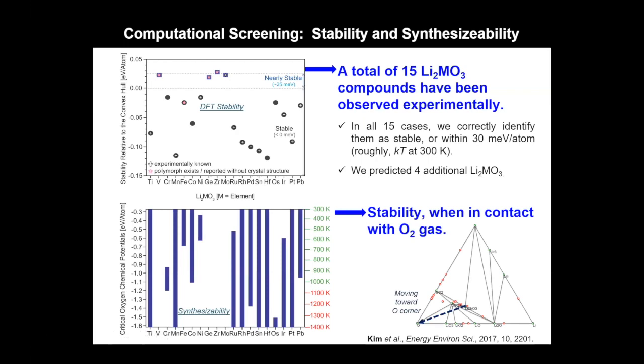We can calculate all sorts of other properties of these materials. For example, if you want to know something about the synthesis and synthesizability of these materials, you can analyze under what thermodynamic conditions they will be stable when in contact with a gas phase species like O2. So you can calculate essentially the stability in equilibrium with O2 as a function of temperature, or equivalently as a function of partial pressure of the O2 gas species.